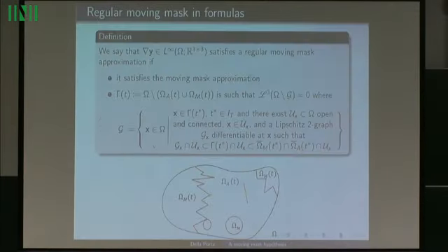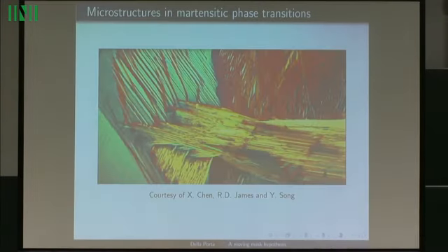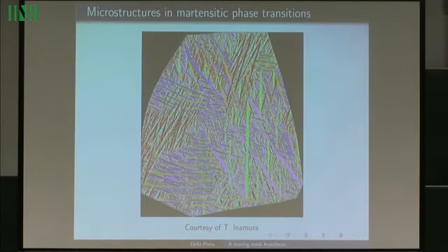However, if you impose that the grain does not deform during the phase transformation, so the shape of the grain doesn't change, and you consider just the 12 deformation gradients given by this formula, then you can prove that no such microstructure is possible.